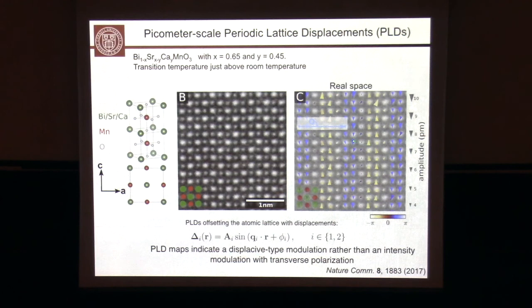Notice also they distort transverse to the order vector. So this is the order vector. This is your stripes. That's where your charge modulation occurs. But instead of going along the charge modulation, it goes transverse. Okay, that tells you bonding is important. And so the ones in yellow go upwards. Okay, so here is this lattice displacement. It has an amplitude term, how strong the modulation is, it has the periodicity Q, that's a Q vector, and it has a phase term. Phase term will be important as we go along,